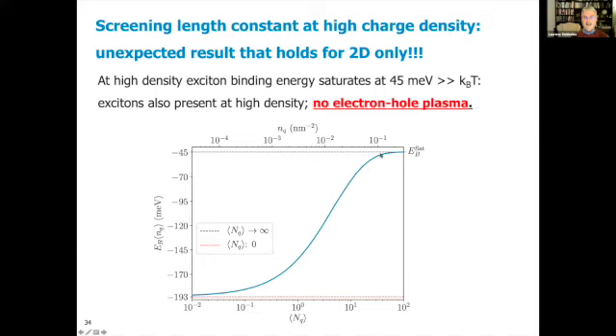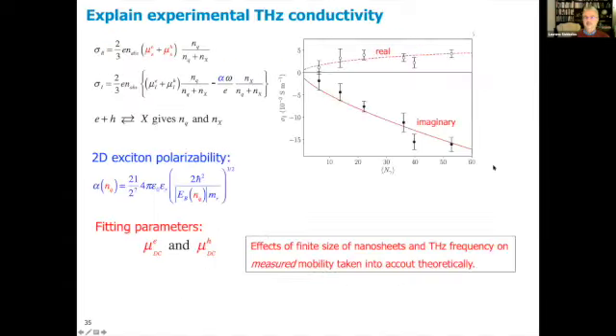So the exciton binding energy saturates even at high charge density at 45 millielectron volt, which is larger than kT, which is 25 millielectron volt. So it's close to twice the thermal energy. So the excitons can also be present at high density, and you get no electron-hole plasma.